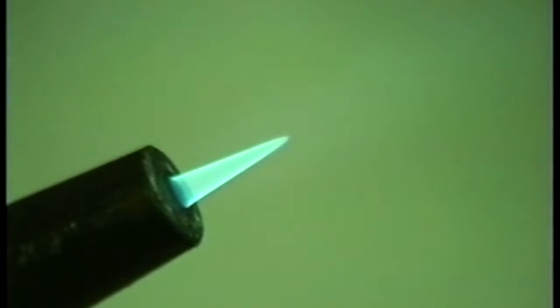If you add too much oxygen, it's called an oxidizing flame. Notice how the inner cone is thinned out and the increase in the rushing noise of the torch. Back to a neutral flame. If you don't add enough oxygen, the inner cone won't be sharp, and this is called a reducing flame. There's an excess of acetylene here. I'll add a little more oxygen, get back to a neutral flame.